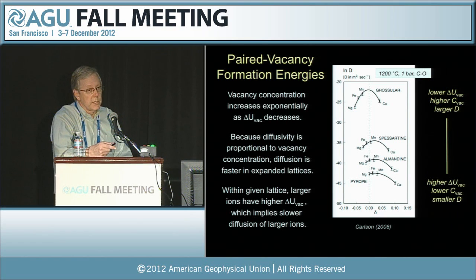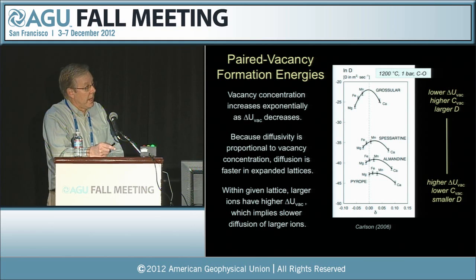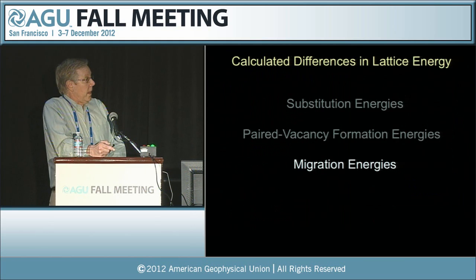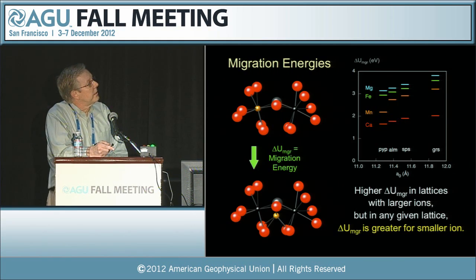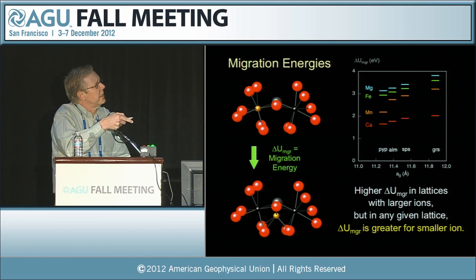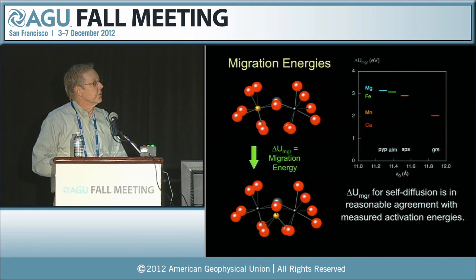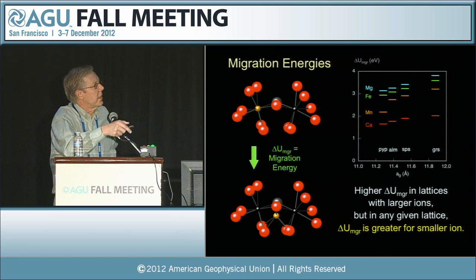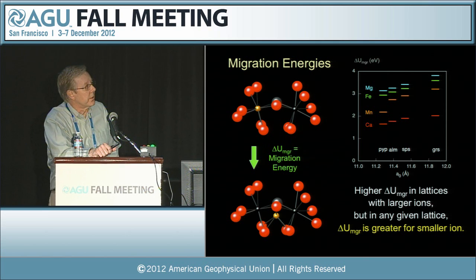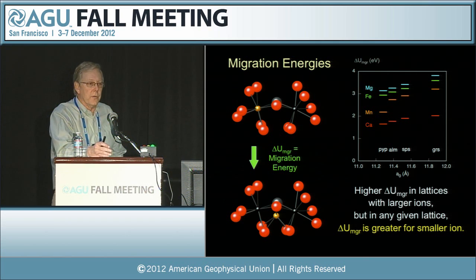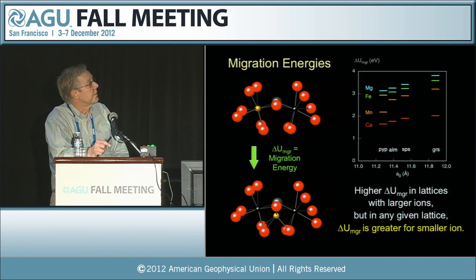Well, that explains what's happening over here on the oversized half of the diagram, but it's exactly the opposite of what we see on the undersized part of the diagram. So we have to look elsewhere for that explanation. And it comes from the migration energies. When we calculate the migration energies, what we see here is that we do in fact have higher migration energies in lattices with larger ions, so that accounts for the slight positive slopes on all of those with a given color. But in any given lattice, the migration energy is greater for the smaller ion, exactly the opposite of what elastic strain theory would predict. And that's a result of the tighter binding of those smaller ions due to the bond length changes when we do the substitutions.